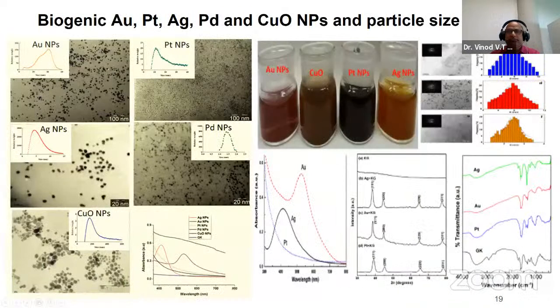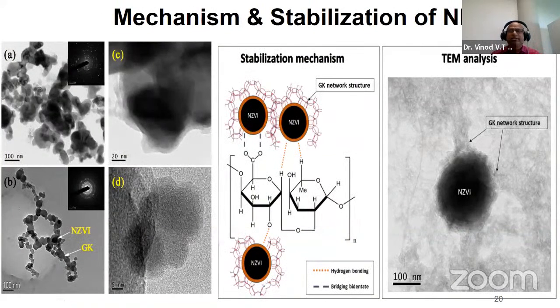These are the characterization steps for nanoparticles. When you use UV-visible spectroscopy, you can find out the corresponding lambda max for each nanoparticle formation, and the color of the solution also changes. It can be analyzed by XRD and FTIR to find out which functional group is responsible for the production of the nanoparticle. And if you want to know the size of the nanoparticle, you have TEM analysis. So these are the main mechanisms of nanoparticle formation and stabilization of nanoparticles using tree gums.